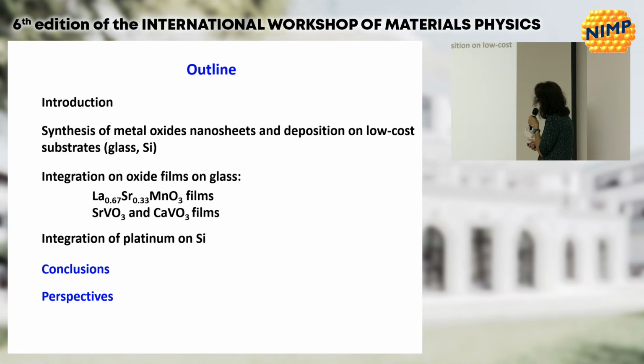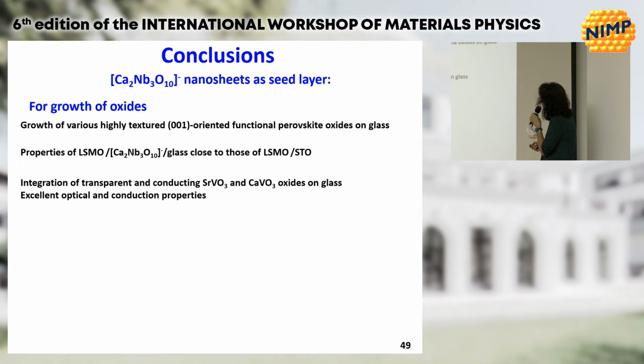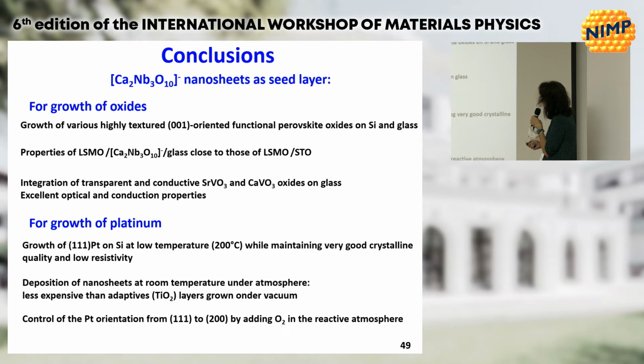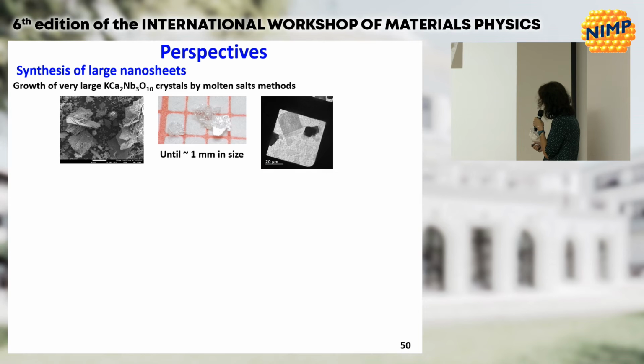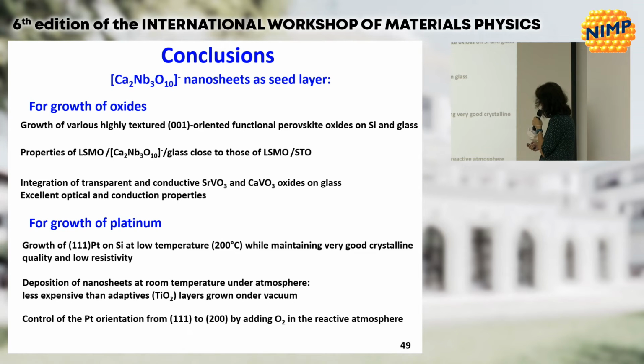So I will come now to the conclusion of the talk. I have shown you that thanks to nanosheets we can grow a lot of functional oxides with properties which are in the state of the art for some of them. And we have some integration of vanadates also, with excellent properties. For the growth of platinum, we have seen that it was possible to lower the growth temperature to 200 degrees, which is a very good result. And also that we can change the orientation of the platinum from 111 to 200 by adding oxygen in the atmosphere.